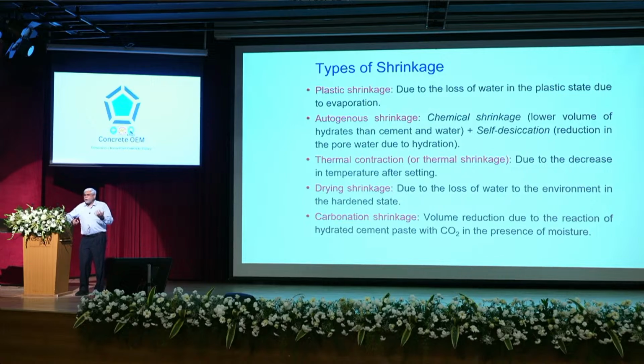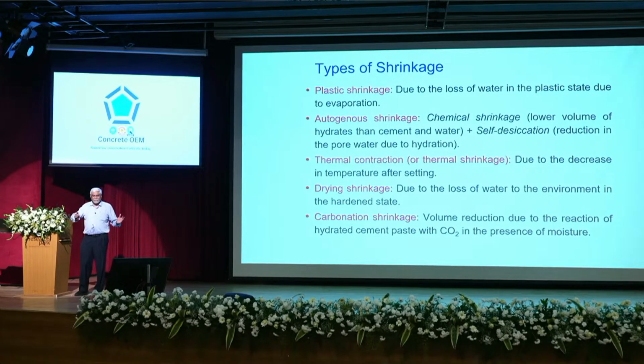Then afterwards, especially when we use high-strength concrete with very little water, the concrete dries up internally. This is called autogenous shrinkage. Then the concrete also is picking up heat. All cement reactions are exothermic. So the concrete is hot. If you touch high-quality concrete after 1 day or 3 days, you'll see it's hot. But the environment is cooler, so it has to contract. The outside is cooling, inside is hot, so it cracks. That is thermal contraction or thermal stress-induced cracking.